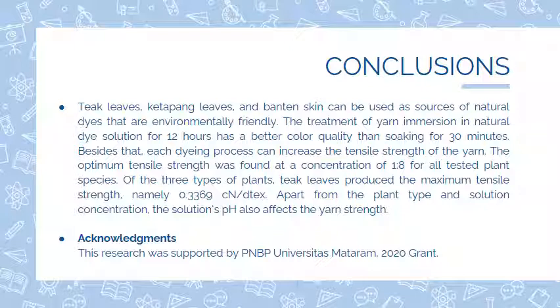That's all the results, and for the conclusions, teak leaves, ketapang leaves, and banten skin can be used as sources of natural dyes. The treatment of yarn immersion in natural dye solution for 12 hours is better. Besides that, each dyeing process can increase the tensile strength of the yarn, and the optimum tensile strength was found at the concentration of 1/8.